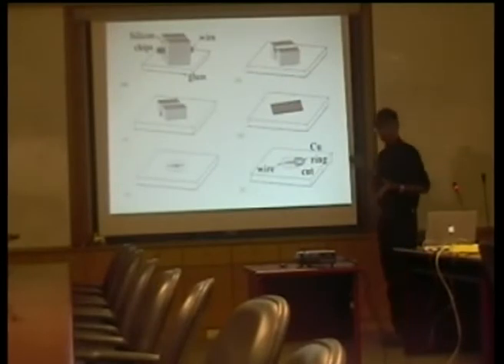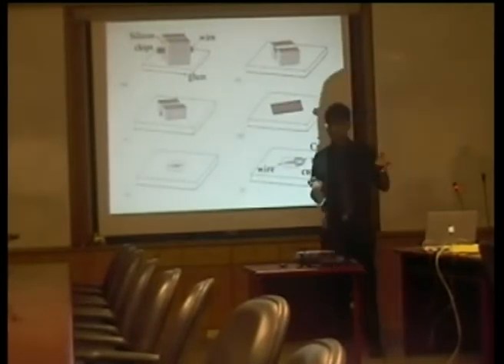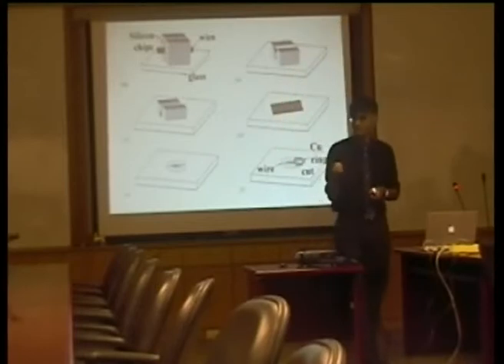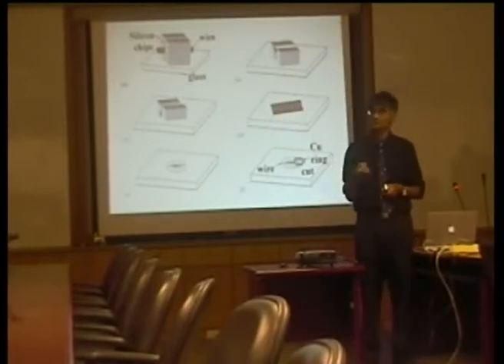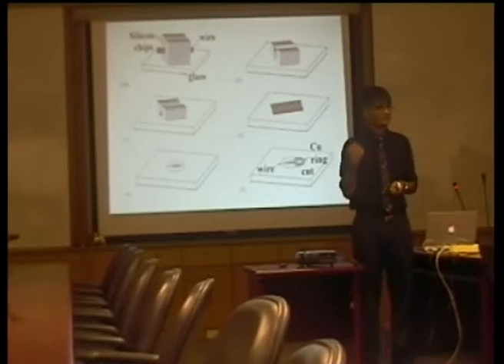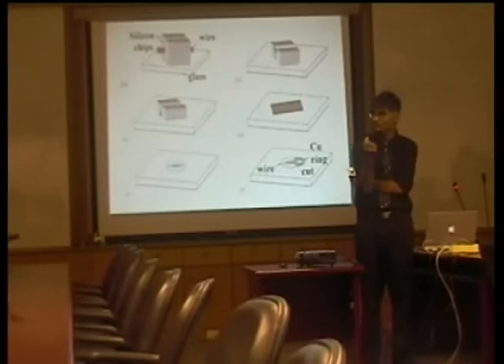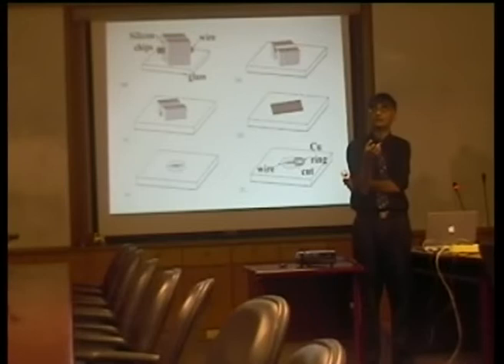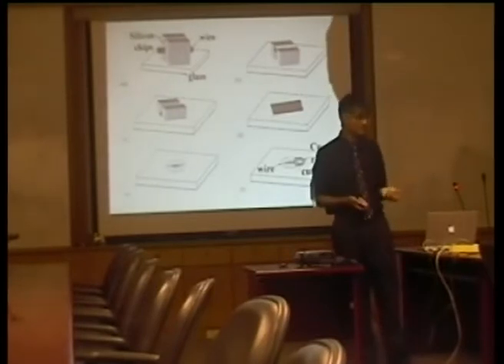And this is the way in which Professor Yang's student prepared the sample in order to examine it in a transmission electron microscope. Now this is a very unusual way of making a specimen, because we are starting with an 8 micrometer wide wire. So there's no question of making a sample, electropolishing it, and so forth. It's just too small to do that. So what they've done is something very clever.